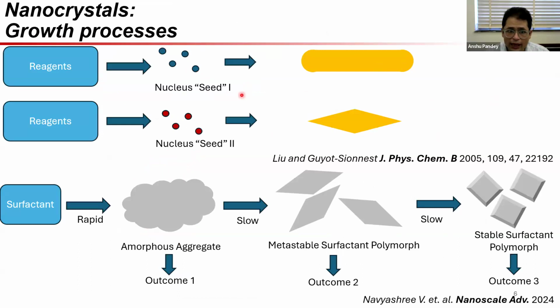This is one wonderful work from long back by Liu and Guyot-Sionnest, where they showed that, in synthesis of gold nanoparticles, you can have two different kinds of nuclei. The only difference between these is that the initial starting reagents used to make the nuclei are different. But when these are plugged into the main reaction, where nucleation and growth are two completely separated events, depending on which nucleus you use, you get a totally different outcome. And this is happening simply because the nucleus is either single crystalline or polycrystalline, and so when it's isolated entirely decides what the reaction outcome is. This is one such example where you can have radical changes in morphology and structure simply given what the original nucleus was, how it was prepared, and at what state it was intercepted.